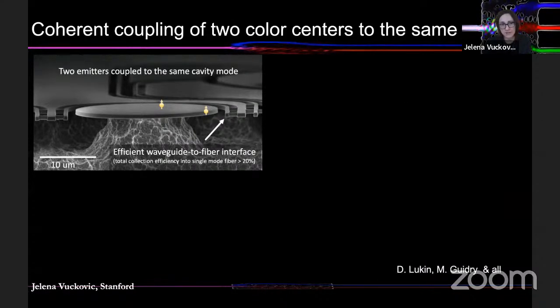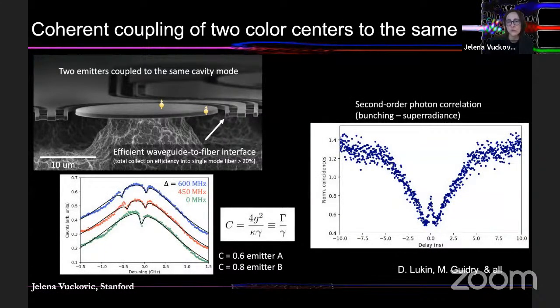And then for coherent interaction, we do see that in the case when they're both coupled to resonance, we do see coherent collective interaction and super radiance from statistics measurements for the system. So as expected, we can actually observe this bunching in the photon correlation measurements, which is actually a signature of super radiant behavior and collective coherent interaction of two color centers with the cavity mode.